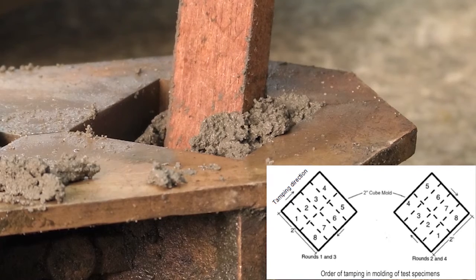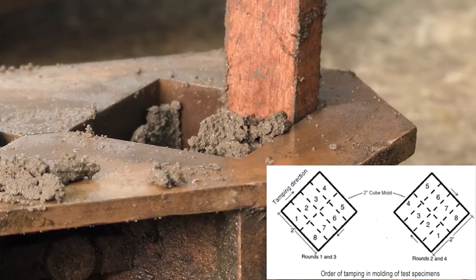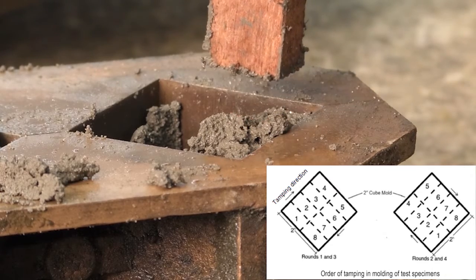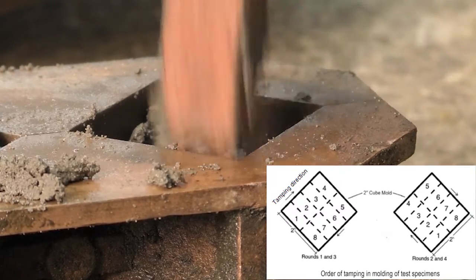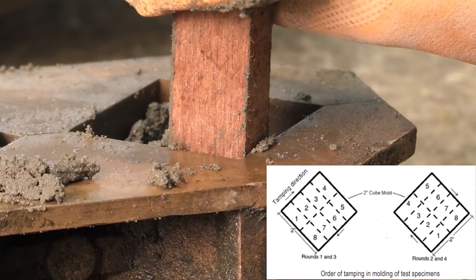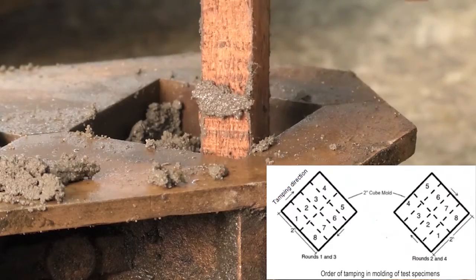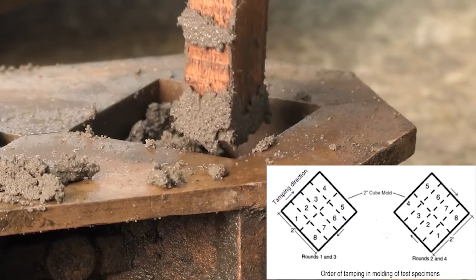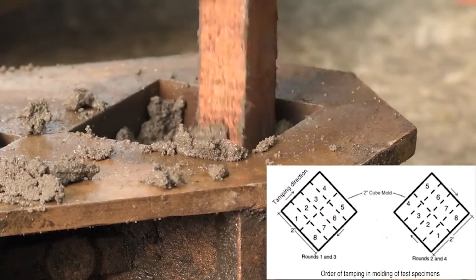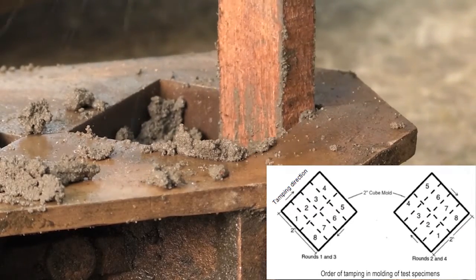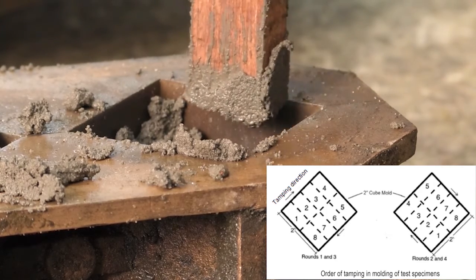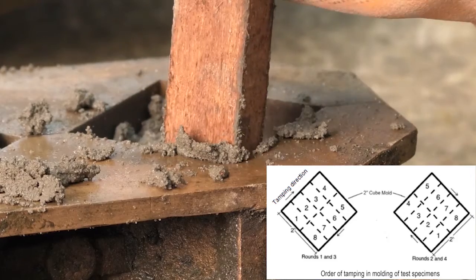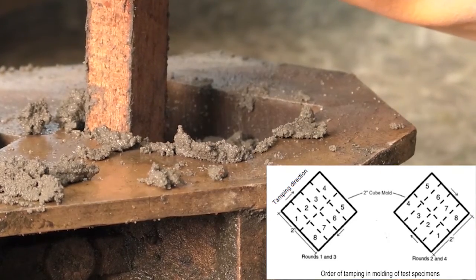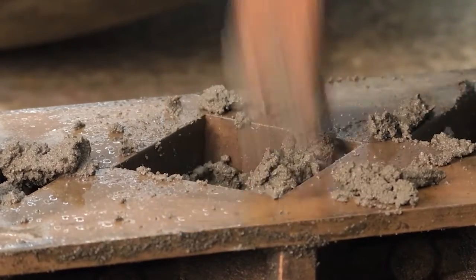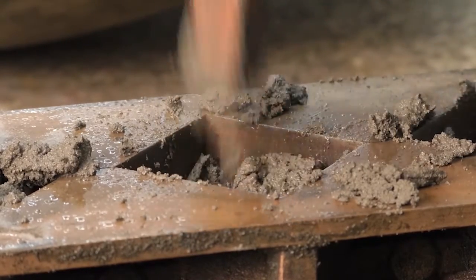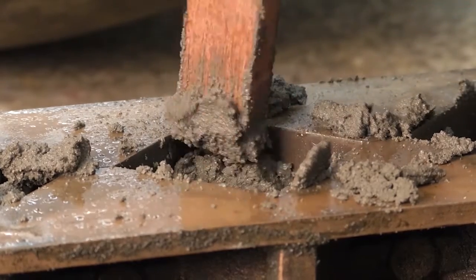Each round has to be at right angles to the other and consists of 8 adjoining strokes over the surface of the specimen as illustrated in the figure at the lower right corner of the screen. The tamping pressure should be just sufficient to ensure uniform filling of the molds. We have to complete the 4 rounds of tamping, that is 32 strokes of the mortar in one compartment before going to the next. Similarly, all 3 of the compartments should be tamped in the same way.